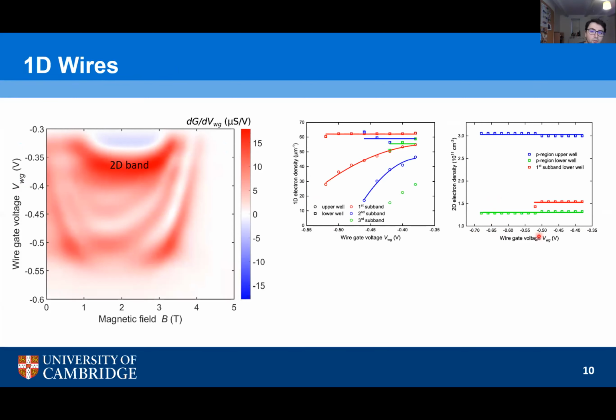And the important thing to notice here, well, two things. First one, here you have the red curve. This is the 2D density below the wires in the bottom well, and the same thing, we call it P region, but it's essentially the injection region into the wires, which is 2D in nature. And you can see that they closely match. What this tells us is that the bottom well, even though we're modulating the top well, remains relatively unperturbed, and as such, it can be used as a well-understood probe.